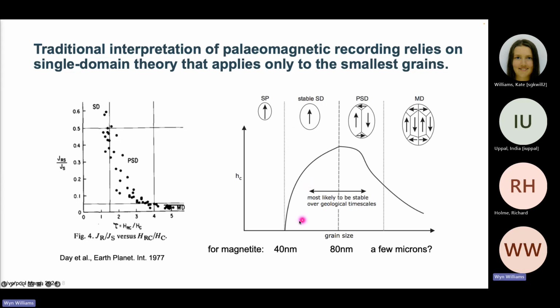So for magnetite, if we look at what the range is, as we know now, at least for equidimensional magnetite, below 40 nanometers is all superparamagnetic. Above 80 nanometers, it's no longer single domain. Of course, that's just for equidimensional, and the range will vary for elongated grains. But for the grain sizes in your samples, it's a tiny, tiny fraction. Hardly any of your samples are going to be perfectly uniformly magnetized. Even single domains vary from the classical stability that you might predict from Néel theory because of the deformation and the slight variations in the magnetic structure within them.